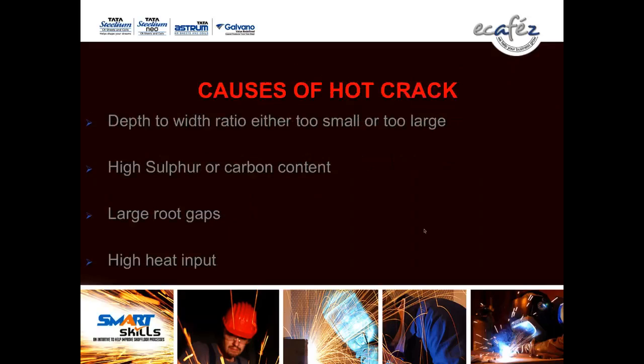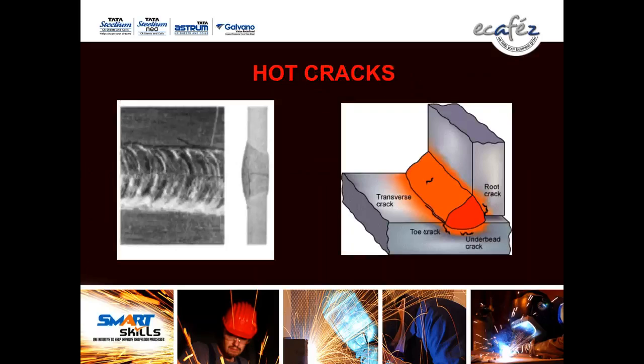Causes of hot crack: depth to width ratio either too small or too large, high sulfur or carbon content, large root gaps, high heat input. These are the causes. These are the pictorial views of hot cracks. You see the transverse cracks, toe cracks, underbead cracks, root cracks, and longitudinal cracks or solidification cracks.